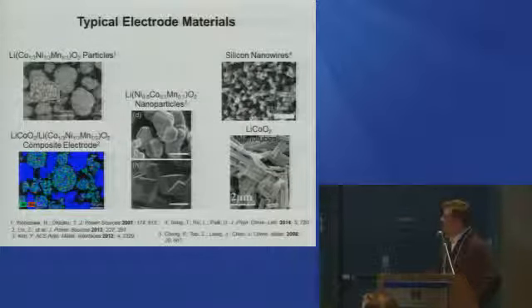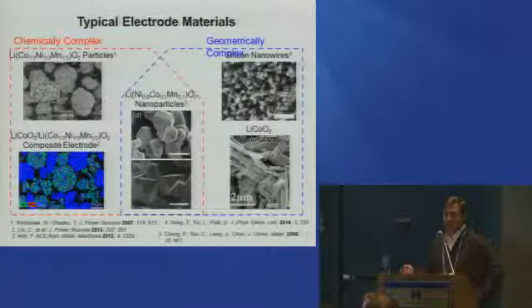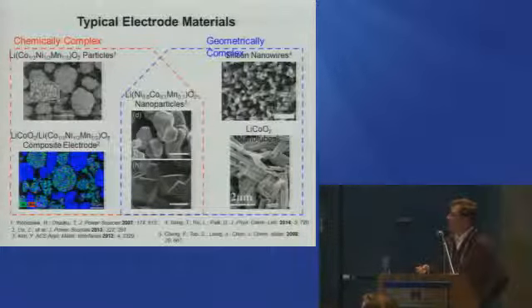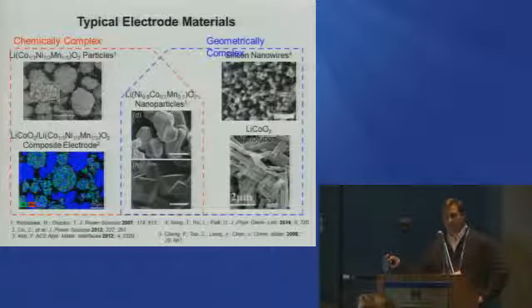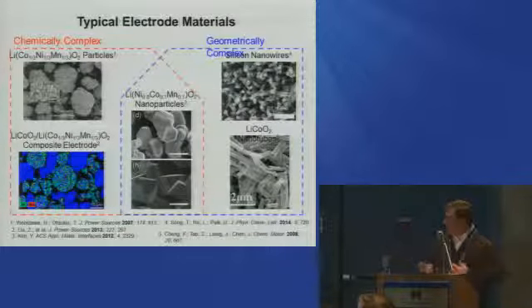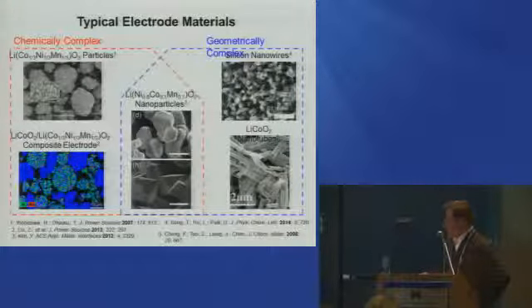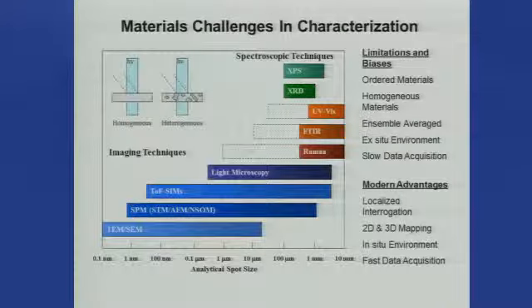So what makes these very difficult materials is that they're both chemically complex, trying to understand the redox chemistry of these different transition metals in these oxide matrices, and how lithium coordinates to those different sites, but also how the issue of morphology and size lead to certain predictive behaviors, such as scalability, of when something goes small or gets big, what limits the lithium ion transport in these materials, and also what influences the degradation chemistry that can occur as a side effect.